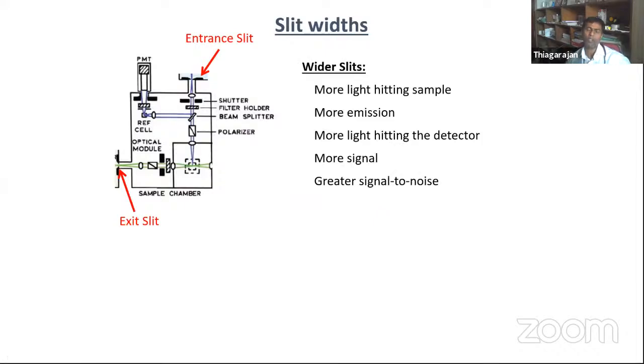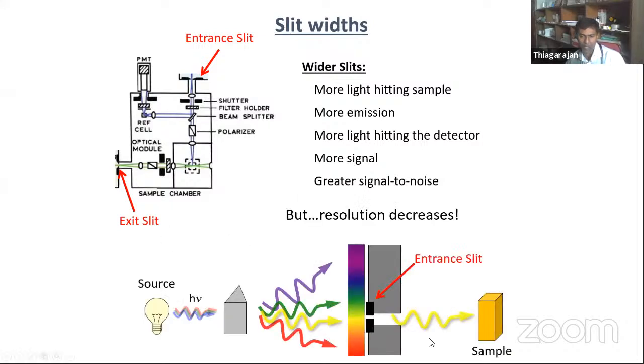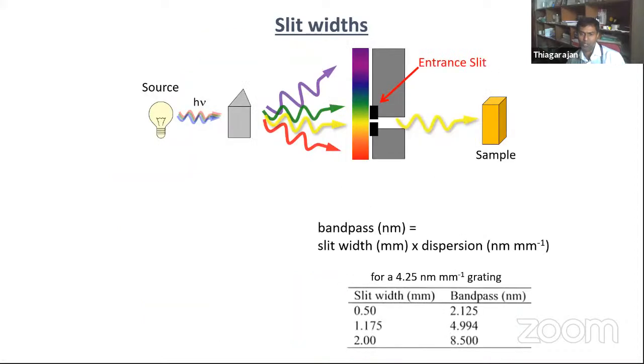When we open the slit, more light hits the sample, more emission, and more light hits the detector also. So more signal, greater signal to noise ratio. These are the advantages. But the main problem is that when we increase the slit width, the spectral resolution, the wavelength resolution, decreases. This is the monochromator, it separates the wavelengths of light. If I want to pass only 400 nanometer through the slit and I increase the slit width, not only 400 passes through the sample, but also 402, 405, and in the same way 398, 396. So we lose the spectral resolution, the wavelength resolution.